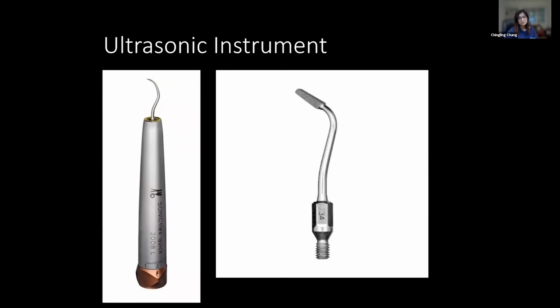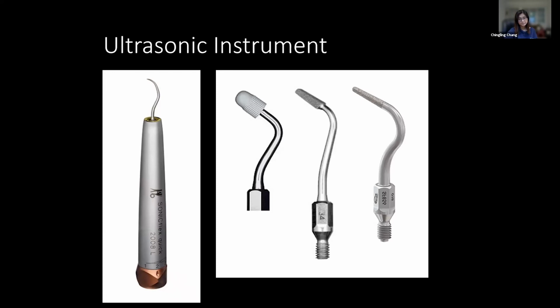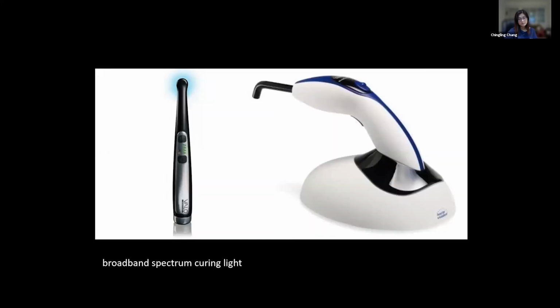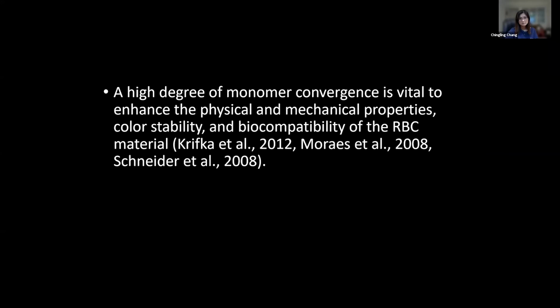And the ultrasonic instrument also helps you to vibrate the composite resin. So the tip on the left is the tip that helps you to seat the onlay into position. And for polymerization, we recommend using a broad band spectrum curing light, so you will be able to have a higher conversion rate of the resin. So a high degree of monomer conversion is vital to enhance the physical and mechanical properties, including color stability and biocompatibility. So we really recommend you use the broad band spectral curing light to get a higher degree of monomer conversion.